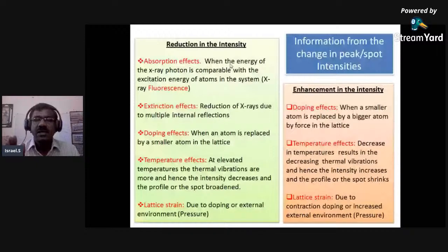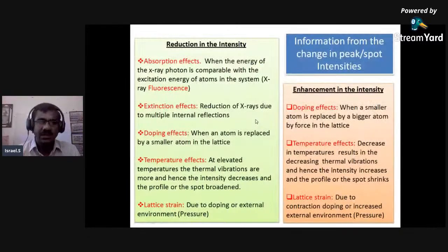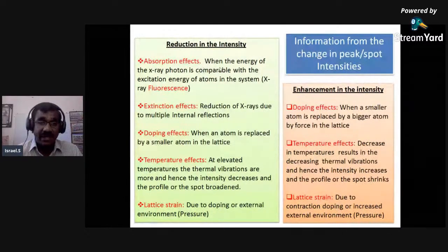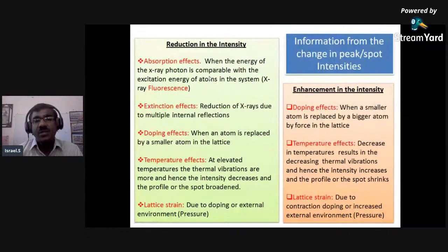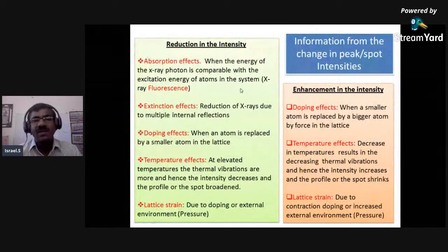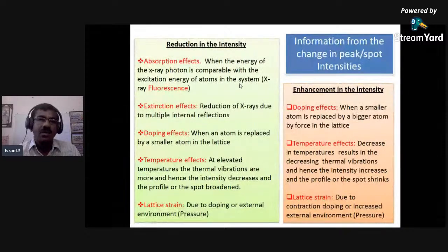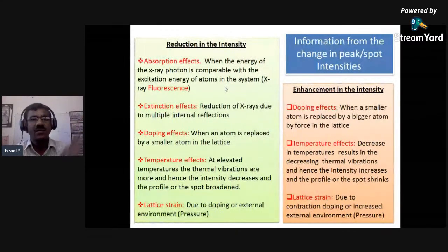If you find that some of the intensity is lost, when there is a reduction in intensity, then of course you can say absorption could have taken place. When the X-ray photon energy is comparable with the excitation energy of any atom in the system, that atom will absorb this energy and go for some fluorescence effect. So whether it is an X-ray fluorescent material, just look at the HKL plane's intensity. If there is an absorption, you can say it's an X-ray fluorescent material.